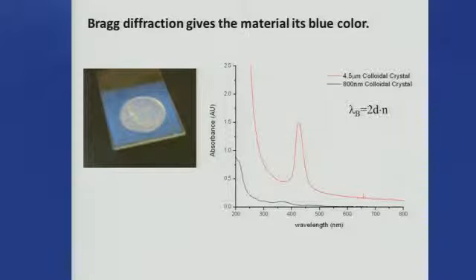these things. And then the trace here is effectively absorbance, so Beer's law. The transmission is reduced when you're at the band gap, and so you get this peak, and the peak is related to the refractive index difference between the air and the material, and so that's why it's a photonic material. And if you make it really, really thin, you start losing the effect of this three-dimensional diffraction grating, and it shifts as well. But they're relatively transparent, except for the place where you have the band gap, and that's what gives it the blue color. So it's very pure silica that we use, but it gets a color because of this Bragg diffraction.